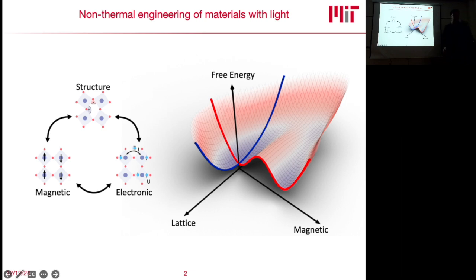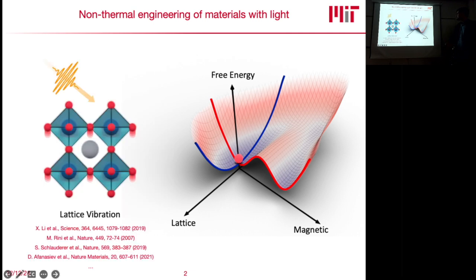And this actually allows you to find favorable pathways around these energy barriers, which you can take to actually, while preserving this low energy ground state, to actually go into these hidden states. And so this is typically done by using low energy light to couple to the fundamental collective excitations of these materials to drive them to large vibrational oscillations, which is shown in this cartoon here, which then allows the system to actually dynamically bypass these potential energy barriers and then end up in one of these hidden states.